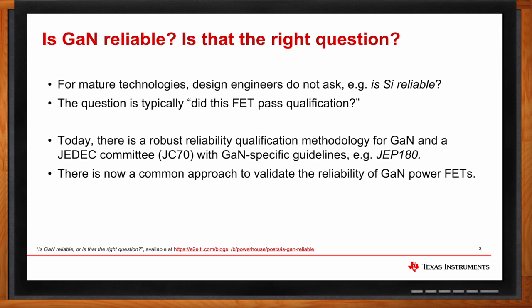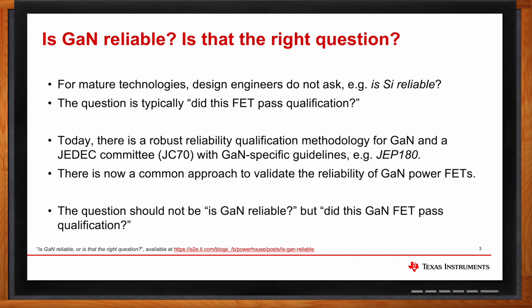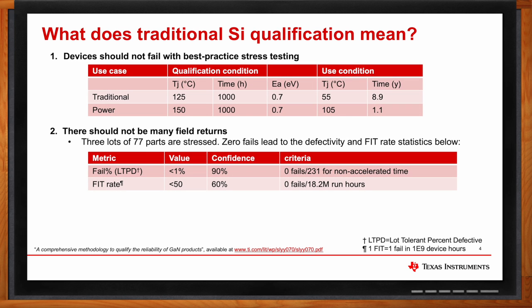So the question is not so much, is GaN reliable, but did this GaN FET pass qualification? Qualification is a process which assures that devices meet a certain level of quality and reliability. It breaks down into two simple steps. First, devices should not fail with best practice stress testing. For the traditional case, devices have historically been qualified at 125°C for a thousand hours, with an assumed activation energy of 0.7 eV. This translates to about nine years of use at a temperature of 55°C. But for power electronics applications, use temperatures are higher — about 100°C — so the qualification temperature may be raised to 150°C, resulting in about one year of usage for the qualification test.